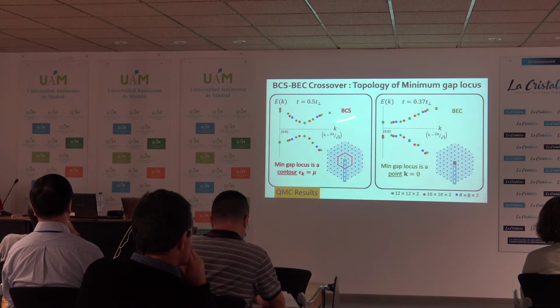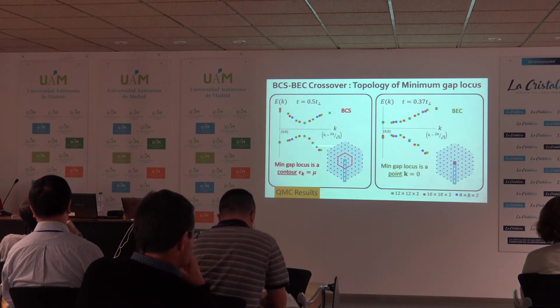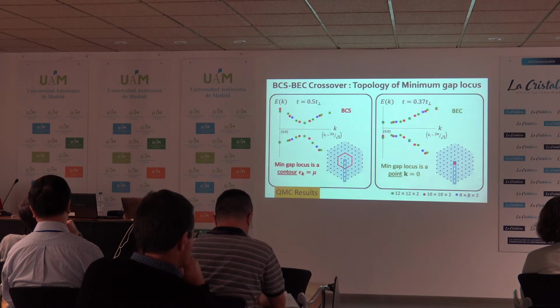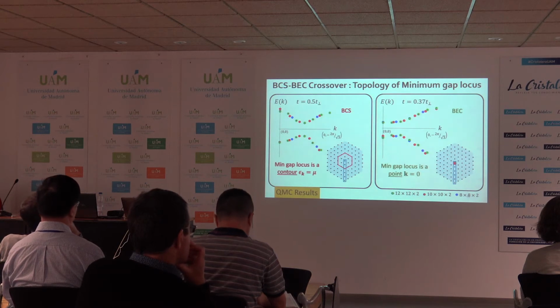Here you see this band bending at a finite value of k. When you map it out, it is this closed contour. Because it's a triangular lattice, it has this shape. And in the BEC side, the band bending happens just at k equal to 0. This whole picture has moved to k equal to 0, and you get that minimum gap locus at the gamma point.